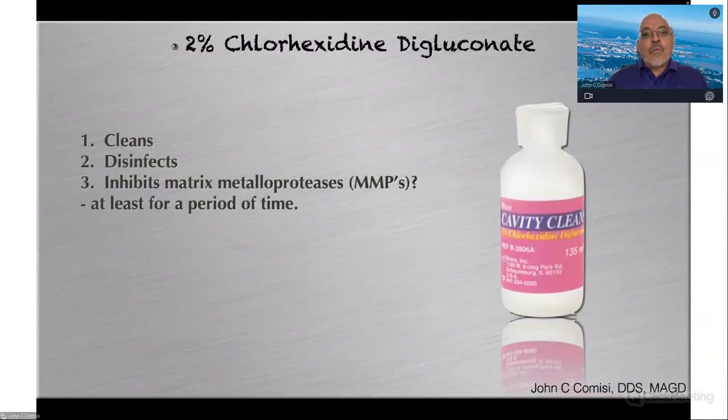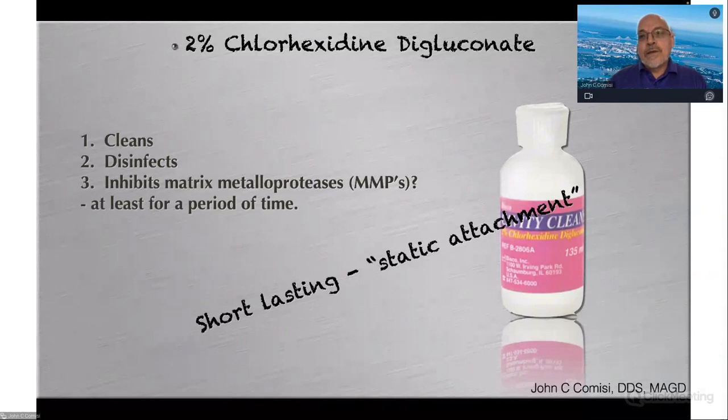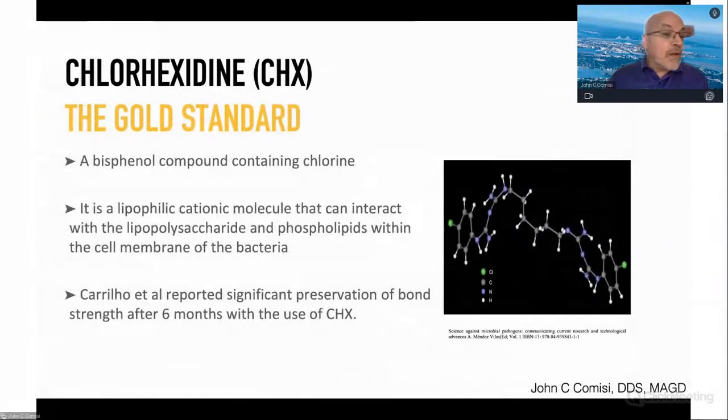Chlorhexidine, of course, has been one of the biggest things that we love to use. It cleans, it disinfects, it inhibits MMPs, at least for a period of time. Studies have shown that it really doesn't give us the long-lasting benefit that we would like. It's kind of a static attachment to the tooth structure that dissipates after a relatively short period of time. It's been the gold standard for so many years because of its capability of destroying bacteria on contact. But the bond strength after 6 months has been reported to be lowered as time goes by.